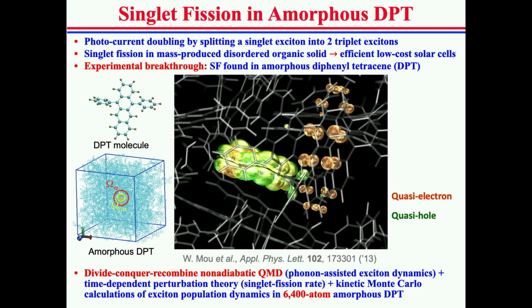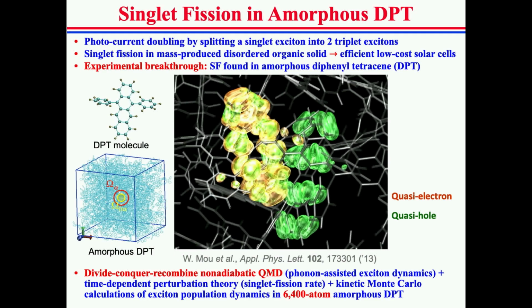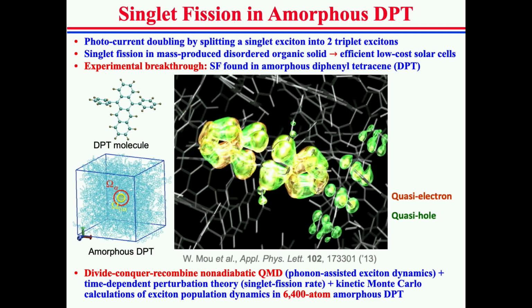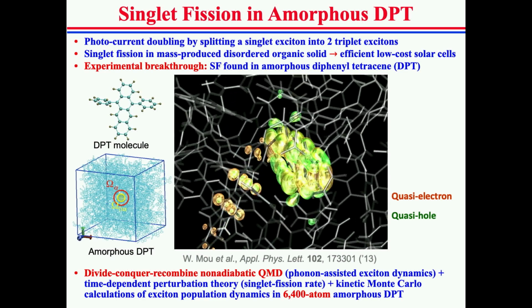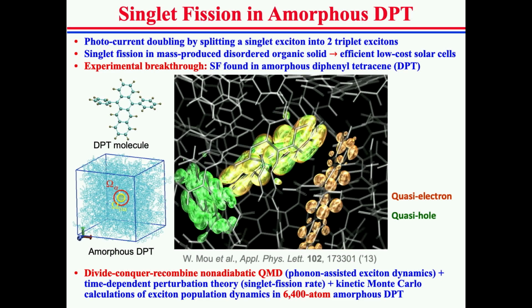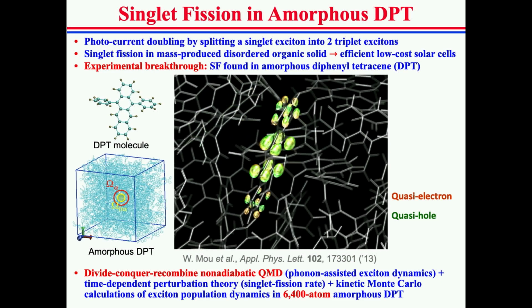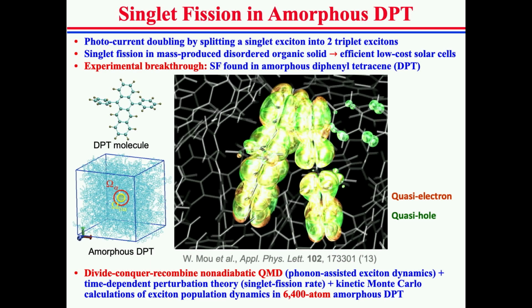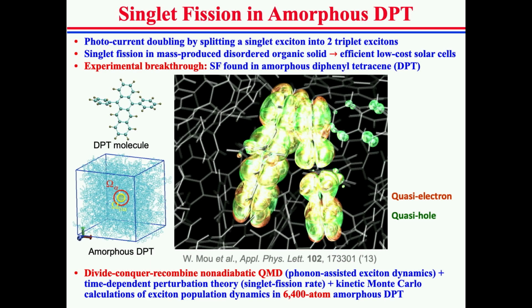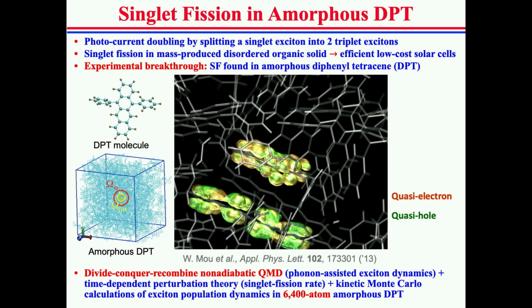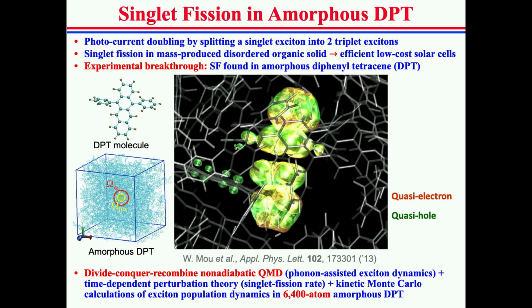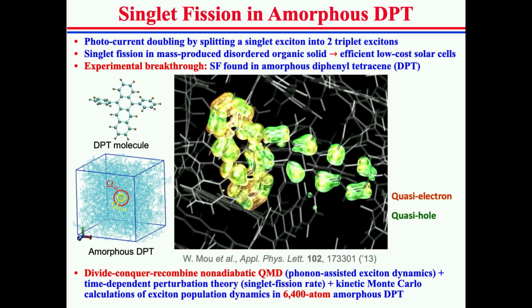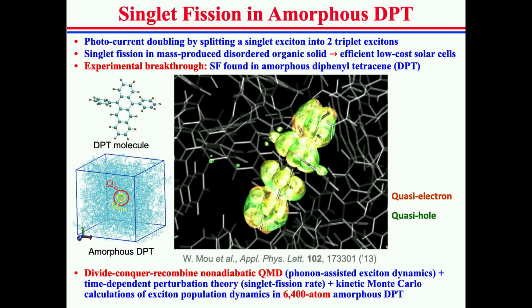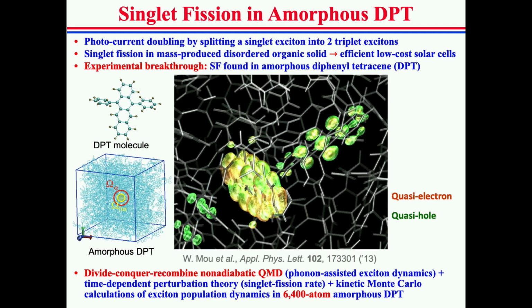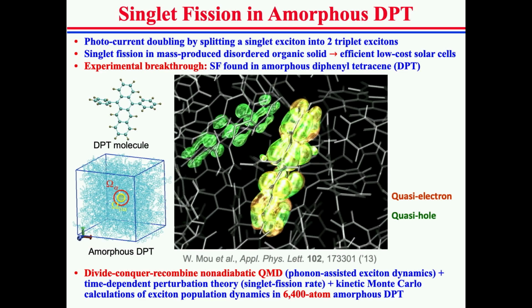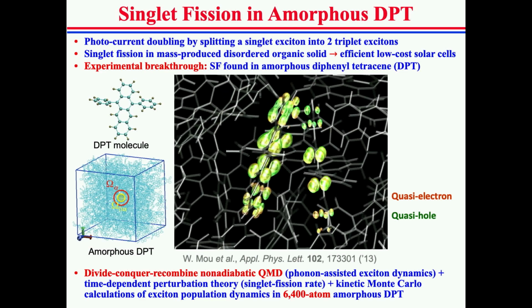At USC, there was an experimental breakthrough to achieve singlet fission in amorphous DPT. That's why we simulated this. Here, we combine the divide-and-conquer-recombine NAQMD to study phonon-assisted exciton dynamics, together with a time-dependent perturbation theory calculation of the singlet fission rate. These rates are recombined in a kinetic Monte Carlo simulation of exciton population dynamics in the 6400-atom amorphous DPT. This shows, again, orange and green for electron and hole.